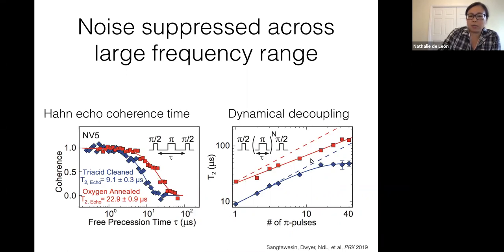And then again, we can apply this dynamical decoupling to probe what happens to the noise at higher frequencies. What we find is that the coherence time is enhanced for this oxygen annealed surface for every single number of pulses that we use. And very importantly, before we do this oxygen annealing, the acid clean surface gives us these NVs that have a saturating coherence time with number of pulses. So you were not going to be able to get away from this noise bath just by applying more and more pulses, whereas we don't actually see any saturation under these better surfaces.